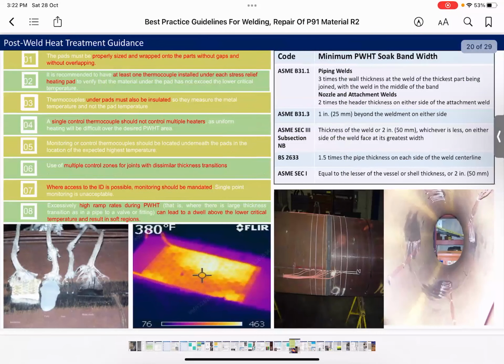So these are the steps that should be verified, carefully monitored and cross-checked before and during the PWHT. We should have inspectors. We should not rely on the contractor who's doing the PWHT. The first thing, maybe not mentioned here, I would like to say about the qualified vendors for PWHT. It is very important to ensure that the vendor doing PWHT has the experience in heat treating or post-weld heat treating of P91 material.